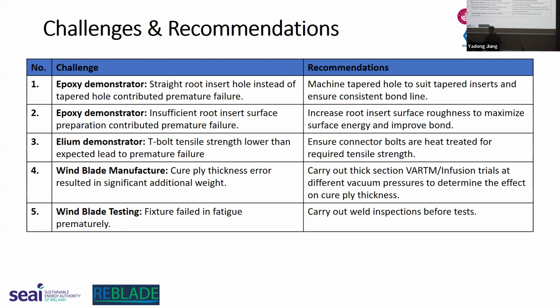Similarly, the root insert surface preparation also contributed to premature failure. So we saw that when the root inserts were pulled out of the 5-meter demonstrator, they were really clean. There was no adhesive residue on them at all. We sandblasted them with a soda medium, and it just dulled the surface, but it didn't really roughen it up as much. So the surface energy could be increased a little bit more. So in a future project, we'd prefer to make the inserts as rough as possible to try and maximize the surface energy and then improve the bond.